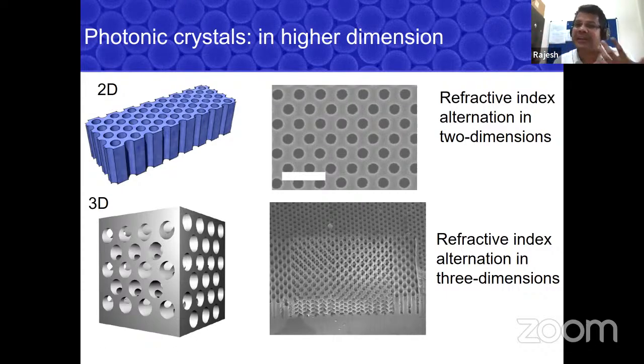And now I can think of the same thing in a 3D periodic system. This is one of the champion structures which people predicted in the 90s and which was experimentally measured in 2011. This is a cartoon picture where you take a box, you drill holes in this way, and you have another set of holes in this way. So these are two interpenetrating sets of holes, and that makes the system periodic in three dimensions. And this is a real sample picture. The top is cut to show you how the pores are well connected within the system. Here one material is silicon, the other material is air. So it's a variation between the silicon refractive index and the air refractive index, which are 3.5 and 1. In whatever direction the light propagates, it sees this periodic variation in the refractive index. And you will really have a band gap for light, because it gives you a band gap in all spatial directions, what we call a photonic band gap.